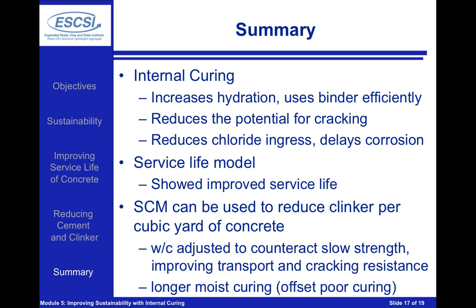which leads to a substantial impact on the sustainability. Second, when we use internal curing with supplementary materials, we're able to reduce a larger portion of the clinker or the conventional cement that's inside of our concrete. Now, this is going to really allow us two main benefits when we start to talk about internal curing. First, we're providing additional water in that system, and that additional water can be useful because our supplementary materials are going to react more slowly. Second, we're able to reduce the potential for cracking, which allows us to adjust our water to cement ratio in a way that's going to allow us to counteract some slow strength development and improve our overall transport properties.